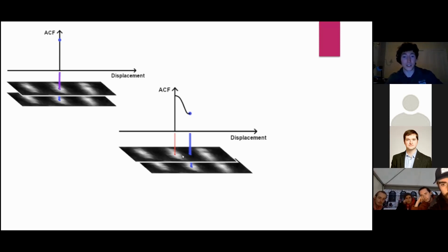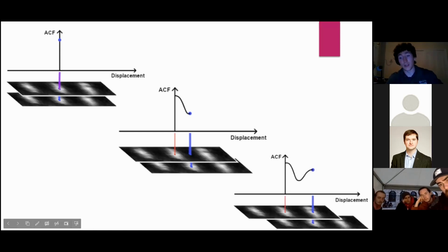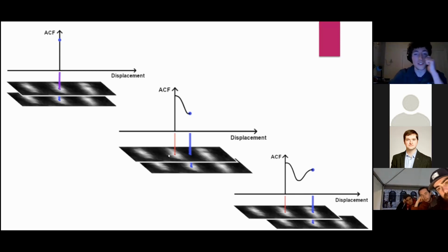A physical crystal. So there's a degree of periodicity here, and that's what we leverage to get out this behavior. Because when you move it a certain distance along that same displacement, you'll get to a point where the intensities again overlap. No, they won't overlap to the same degree, because obviously you've moved your picture and they're not exactly the same point spread functions, but your autocorrelation function will again go to another maximum. This gives us a rough gauge for this width. So we don't actually need to model the point spread function.